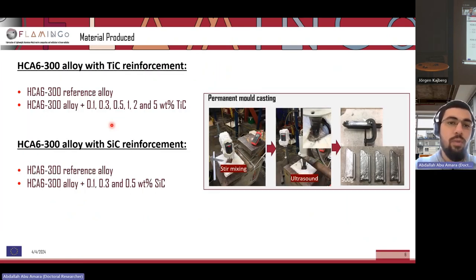So in terms of the materials that we actually produced, this is, let's say, a quick summary. For the materials containing titanium carbide reinforcement, first of all, we have to cast the reference alloy, just the HCA6 300 by itself without any additions. And then we cast the alloy with the addition of 0.1, 0.3, 0.5, 1, 2, and 5 weight% titanium carbide.